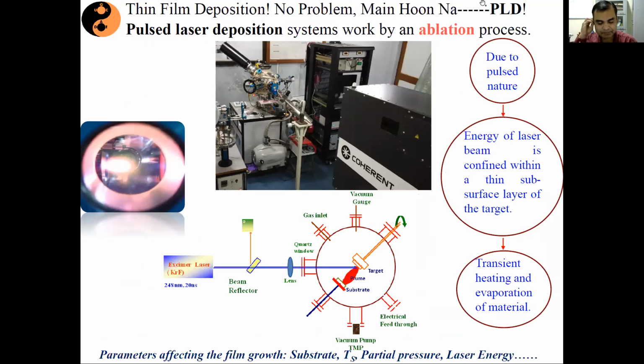How do we get that done? In pulsed laser deposition, we have a pulsed beam of laser interacting with the target material. And remember that the pulse duration is like 20 nanoseconds. And that laser beam, suppose, has an energy of say 200 millijoule. So that 200 millijoule laser energy is transported to the target material in 20 nanoseconds. And because of that, the power that it generates is given by energy per unit time, 200 millijoule divided by 20 nanosecond, that is like 10 megawatt.